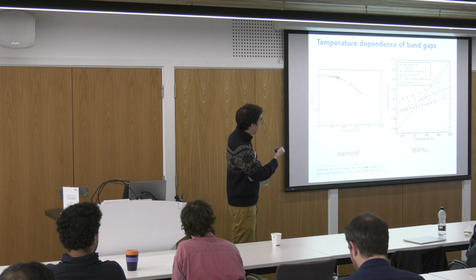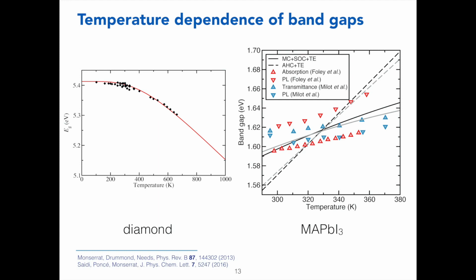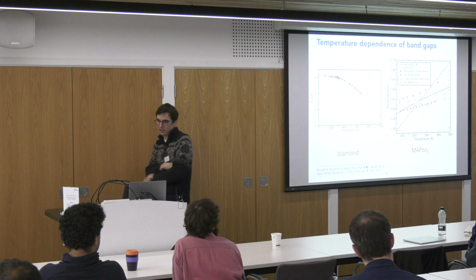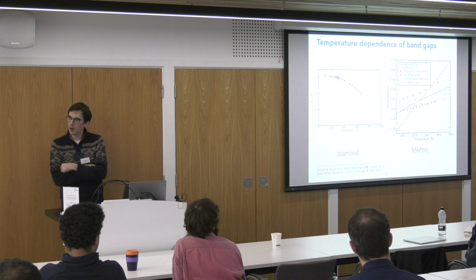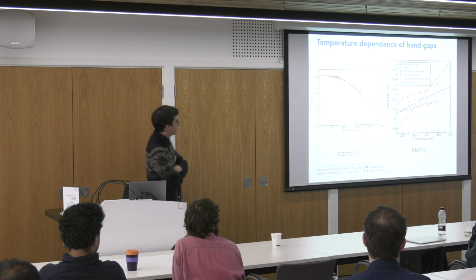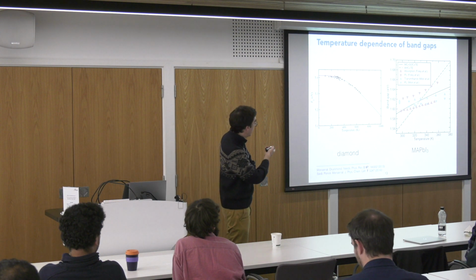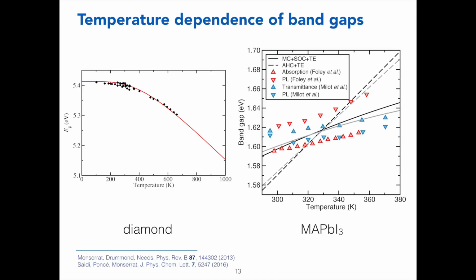On the right, I'm showing, again, temperature dependencies of band gaps on a much narrower temperature range around room temperature. The scale here is also much narrower. Again, I'm comparing theory and experiment. But now here I'm looking at a much more complex material, methylammonium lead iodide, which is, again, one of these hybrid perovskites that has come up multiple times during today's discussions. And we have a number of experiments, which are the red and blue triangles.